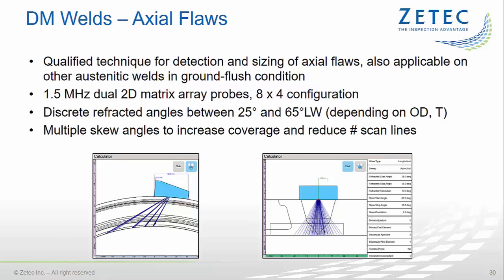For axial flaw examinations, the ultrasonic beams are oriented essentially parallel to the weld. A multiple line inspection sequence is used to fully cover the examination volume. The skewing of the beams is used to reduce the required number of scan lines, and therefore the total inspection time. 2 scans are performed, one with the beams aiming in the clockwise direction and one aiming counterclockwise.